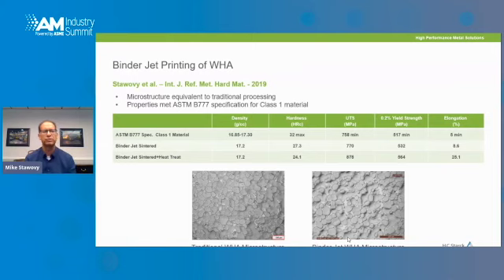You have the specification values shown in the table, as well as material that we've tensile tested in the as-sintered condition and the as-sintered and heat treated condition. In both cases, we meet all the requirements of ASTM B777 with this binder jet printed and sintered material. When we add in the additional heat treatment, we see some improvements in the mechanical properties in terms of tensile strength and elongation to failure.